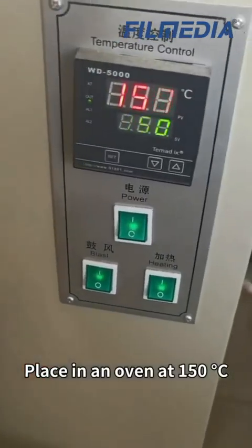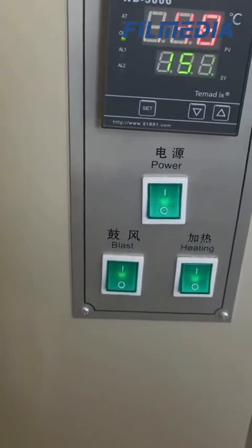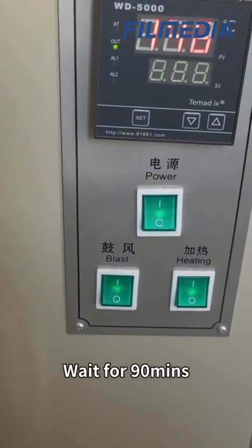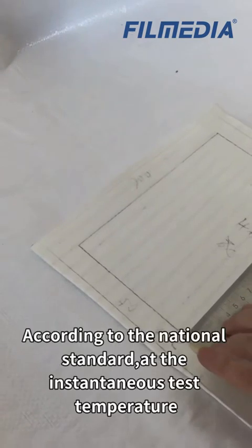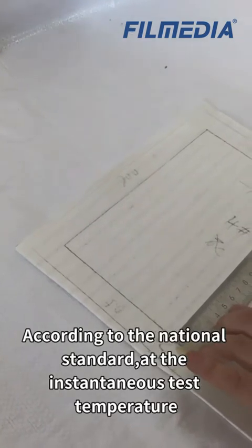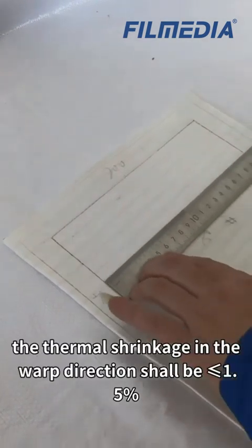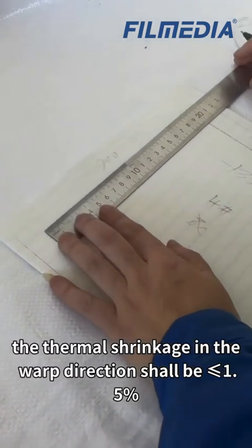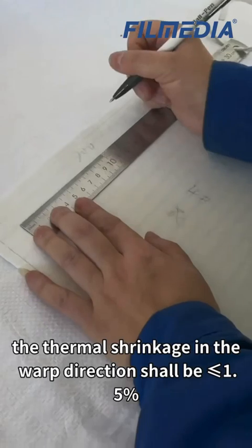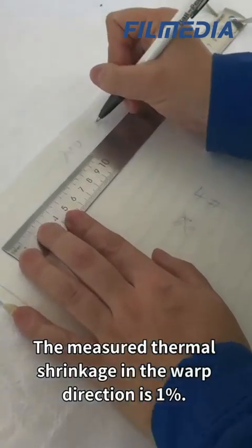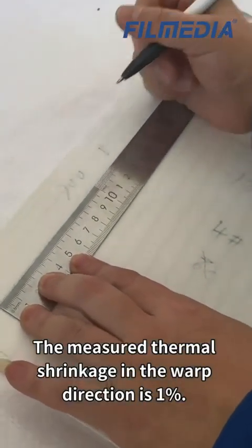Place in an oven at 150 C. Wait for 90 minutes. According to the national standard, at the instantaneous test temperature, the thermal shrinkage in the warp direction shall be less than or equal to 1.5%. The measured thermal shrinkage in the warp direction is 1%.